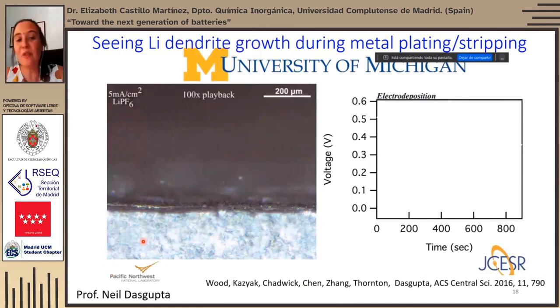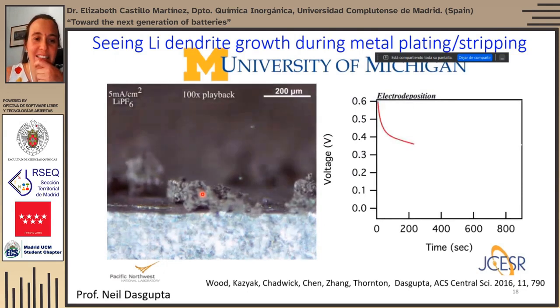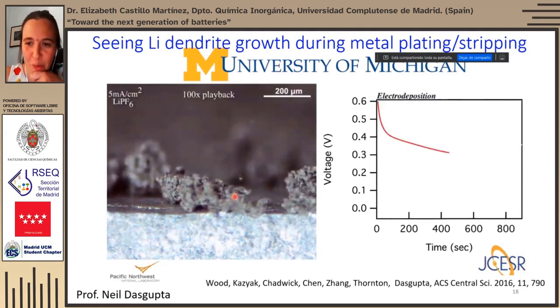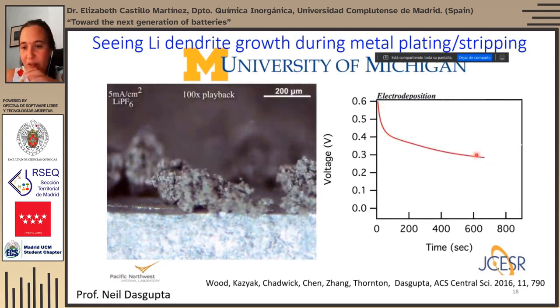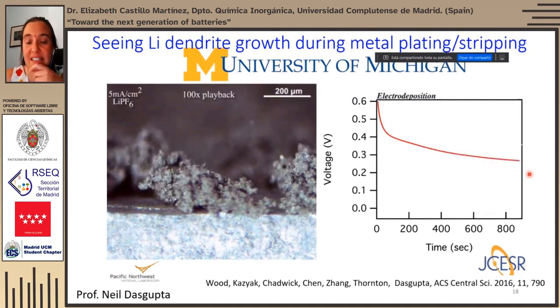Yeah, I'll move on. So what lithium does, instead of forming a homogeneous thin film, it does grow in a very inhomogeneous way, forming dendrites. And these dendrites tend to grow towards the opposite electrode, and sometimes they cross the separator and reach a short-circuiting event. Oh, here it is. You can see the inhomogeneous growth while we are going down in voltage towards lithium 0 volts.